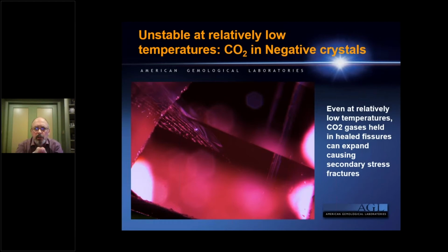Some of the things that you can look for, like look at healed fissures. You have negative crystals and communication tubes present in healed fissures that sometimes contain CO2-rich fluids. And as you elevate the temperature, the CO2 gas expands, and it'll actually cause low relief secondary fissures, like what you see here, extending off the healed fissures. This is a good sign that this stone is experiencing relatively low temperature heating. Here, as you see, there's an unaltered rutile silk, which is still present, but we have features such as this that can start to give you an idea.